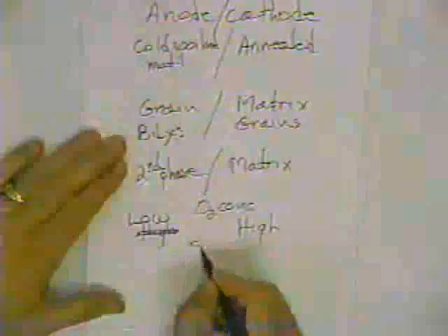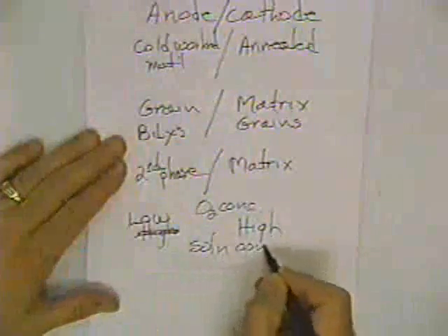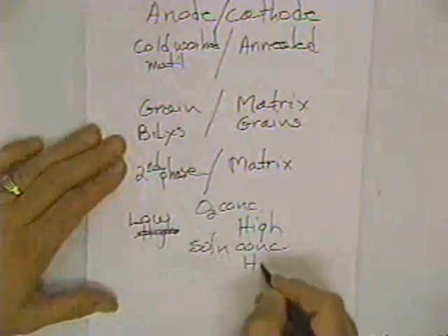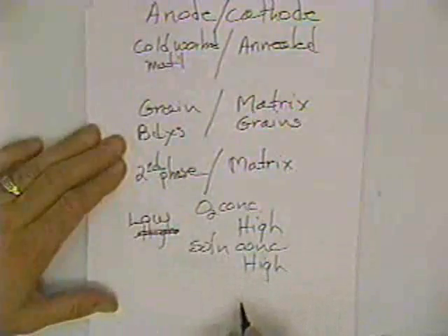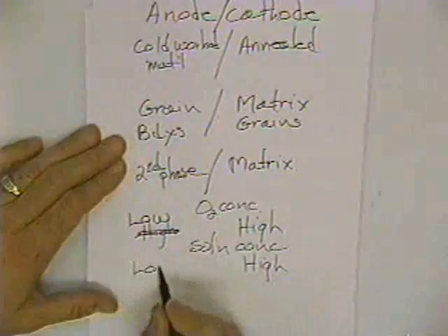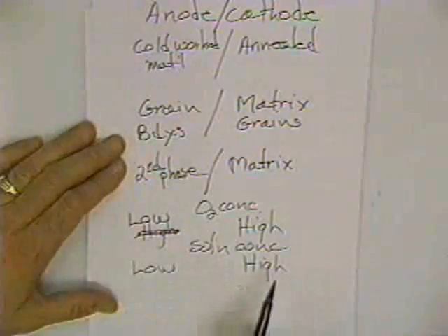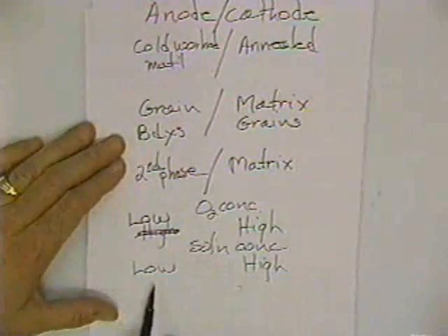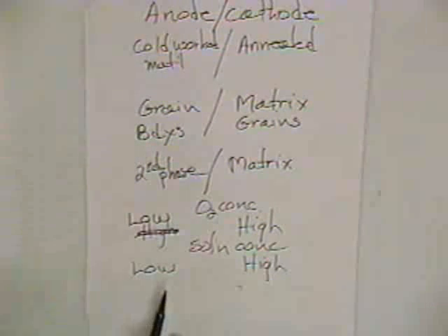If you only have a solution like a seawater on an offshore platform, if you have soil and a structure in the soil, it's not uncommon to have oxygen concentrations. And similarly, solution concentrations can do the same thing. If you have a solution concentrations that's high on one part, lower on the other part, the high side will be cathodic, the low concentration will be anodic.